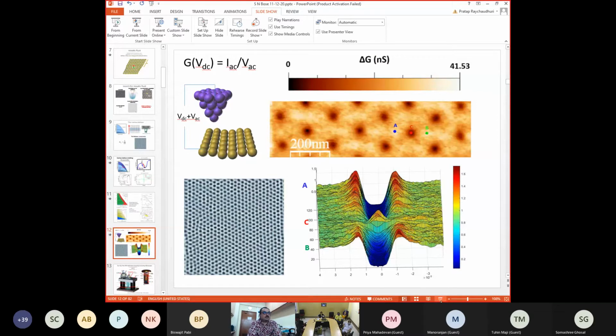Alright, so the way we image vortices is like this. You come with this normal metal tip onto this superconductor. This sample now is a superconductor, and I have applied a magnetic field to produce vortices. When this tip, let's say, is at point A here, I don't have a vortex at point A, so I am tunneling from a normal metal to a superconductor. Now I move the tip and I come to point C. Now remember, the core of the vortex is a normal metal. So when I am at point C, I am tunneling from a normal metal to a normal metal. Then I go again to point B, and I am again tunneling from a normal metal to a superconductor.